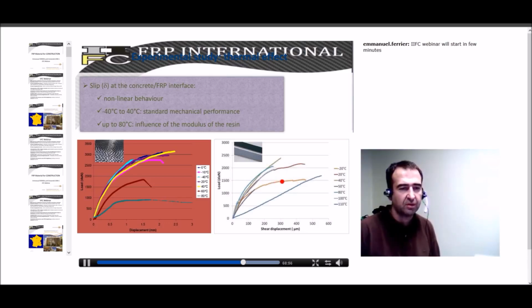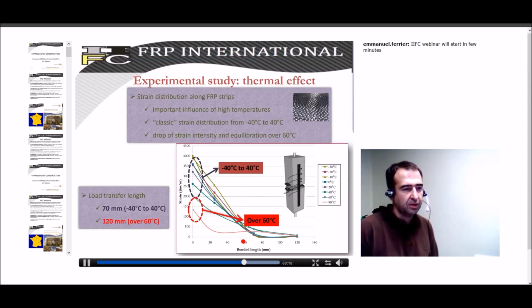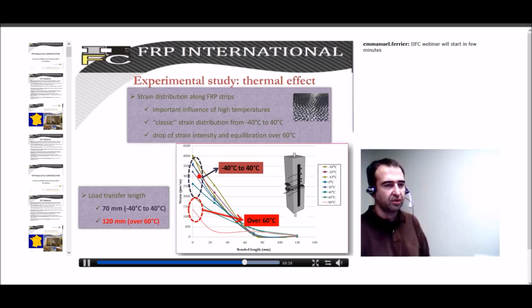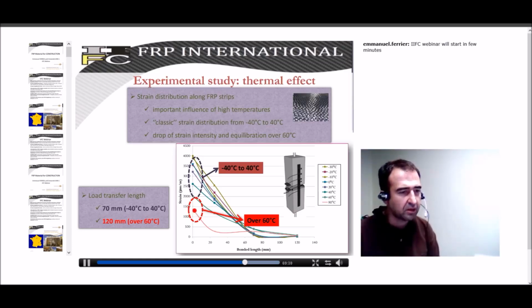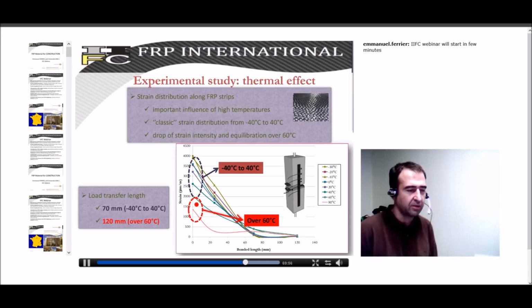But an interesting result is for lower temperature. It seems that there is a decrease in strength at -40 Celsius. It can maybe be explained by more important internal shear stress in the adhesive due to the important difference of temperature between concrete, laminate, and so on. If we look at the strain distribution, you can observe here, at the same level of load, the different strain profiles we get for the wet layup application. We have quite a classic strain distribution for temperatures from -40 to 40. But when the temperature increases, the length needed to transfer the forces increases, and the transfer of forces is very different, with a lower strain at the beginning.